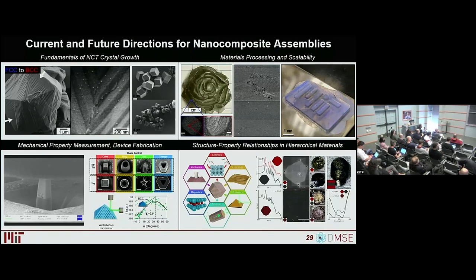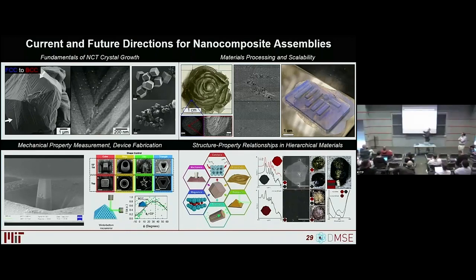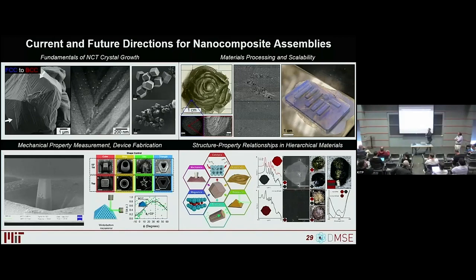It's because the structures that we would see are not the same ones. So this hexapodal type structure and that dodecapodal type structure with the FCC, they're not dominated by any sort of crystalline vector. If you talk about a traditional atomic crystal, there are arguments of stiffness and surface tension that dominate which vectors the crystal can actually grow into. With these materials, it's the underlying shape that pushes these things in this diffusion limited process. So it's analogous to what you're talking about in the sense that you can start with a particular shape and grow it along different directions. But in terms of the correlation between the unit cell and the shape we get, what we find is there simply isn't one. But aren't they just grown from the vertices?